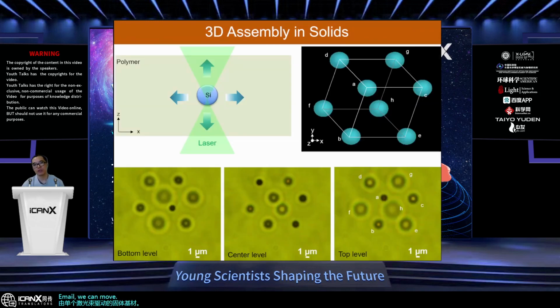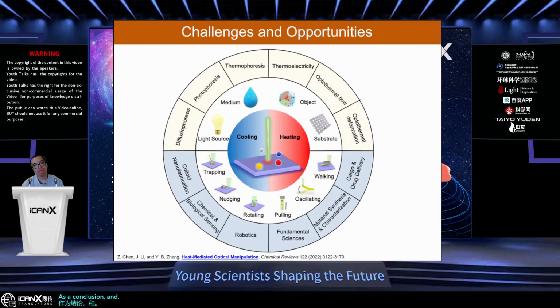We can even move into three dimensions in the polymer matrix to achieve three-dimensional manipulation of the silicon particle here. So we can create very interesting structures using this silicon particle as a building block in a three-dimensional version. So as a conclusion, the field of optothermal fluid coupling can lead to new capability to manipulate particles and cells in various modes, depending on the light source, medium, and what kind of substrate. There are more phenomena we can explore beyond what I just mentioned, the thermoelectric and the optothermal flow. Then, like photophoresis or diffusiophoresis, even deformation can also be induced by the optical heating effect.